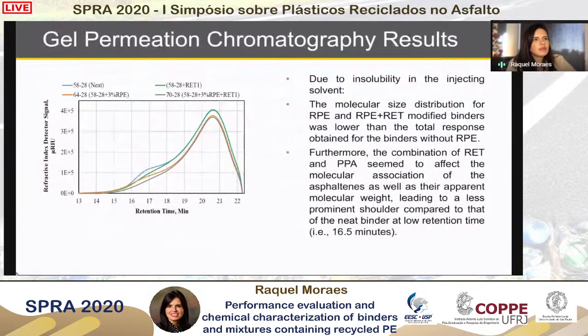And lastly, for the chemical analysis, we performed gel permeation chromatography. One thing that is important to mention is the solvent that was used for this evaluation. The material, the recycled plastics, is not 100% soluble in it.